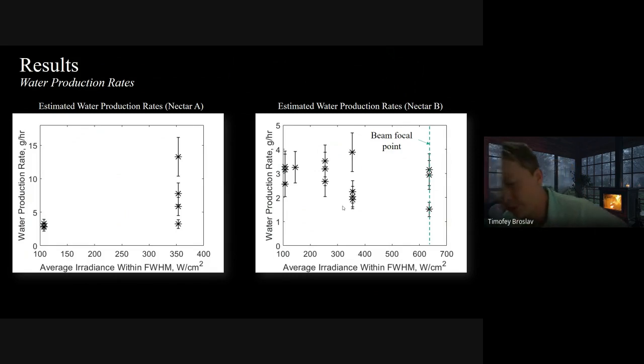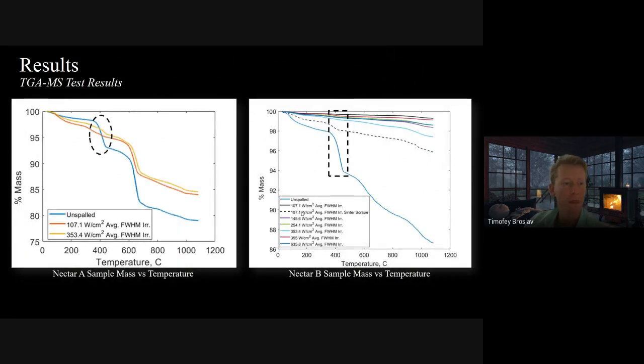Now, this is tied to the surface refresh rate. The water production rate was tied to the excavation rate, because as more material is being excavated, more of it is being refreshed. So the dry material is gone, and you have less dry material that can evaporate water, or I wouldn't say evaporate, dehydroxylate the water from the minerals and so on. So you have this refresh going on. This was not happening for Nectar B. You just have a melt zone that, once desiccated, has really low to no water production.